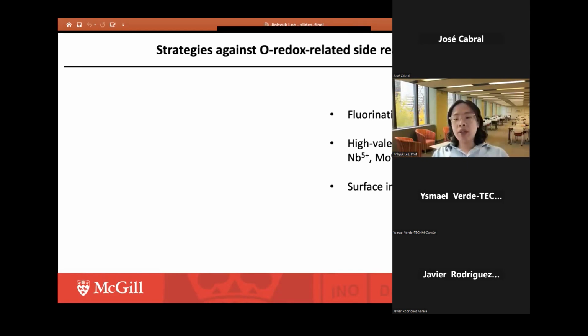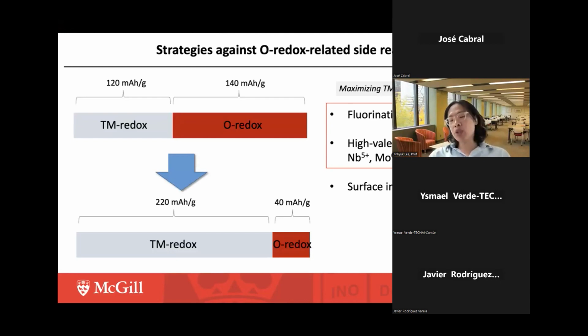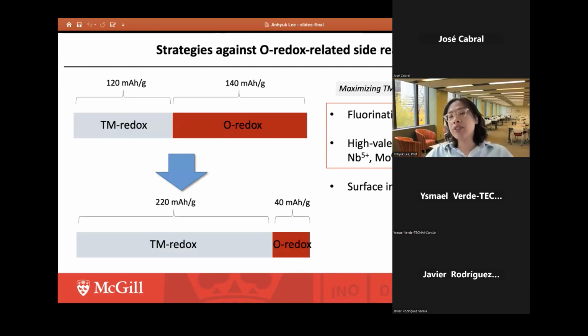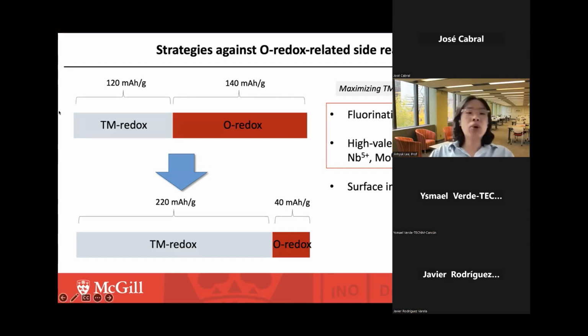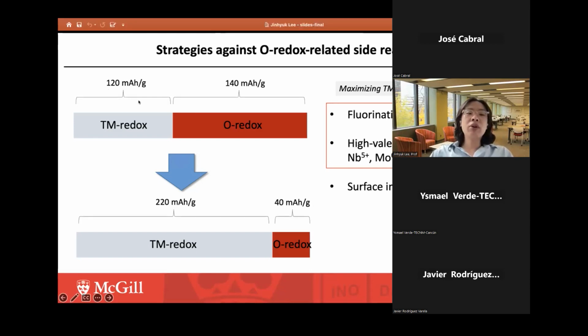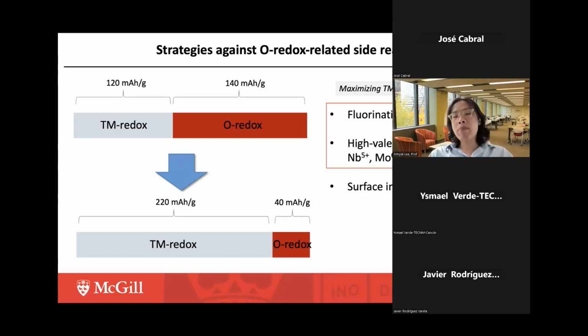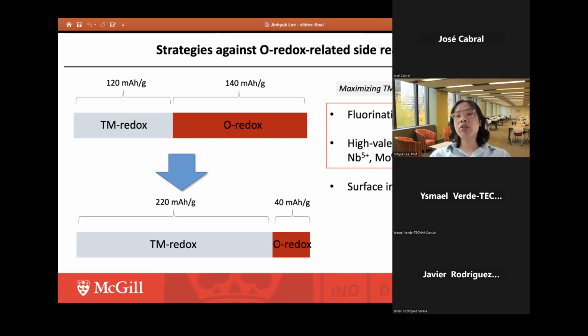But instead of going through all of them, I'm going to just discuss the combination of fluorination and high valent cation substitution to show that we can actually fight against this oxygen redox related side reaction. So basically, combining fluorine substitution and high valent cation substitution with the given lithium excess composition, we can actually maximize the transition metal capacity. So we don't have to rely much on the oxygen redox, and we can avoid this oxygen redox related side reaction. For example, let's imagine we have some lithium excess DRX material which relies on 120 milliampere per gram from the transition metal redox and 140 milliampere per gram from the oxygen redox. In this case, there will be a lot of oxygen redox related side reaction. So what if we change the composition so that, although this is still a lithium excess material, we increase the transition metal capacity to, let's say, 220 milliampere per gram. So upon achieving 260 milliampere per gram, we only rely on 40 milliampere per gram from oxygen redox, to avoid this oxygen redox related side reaction.